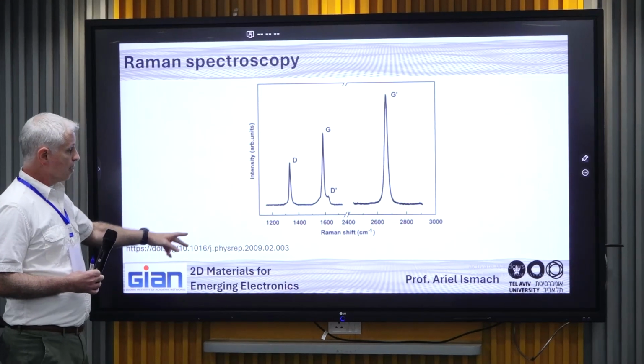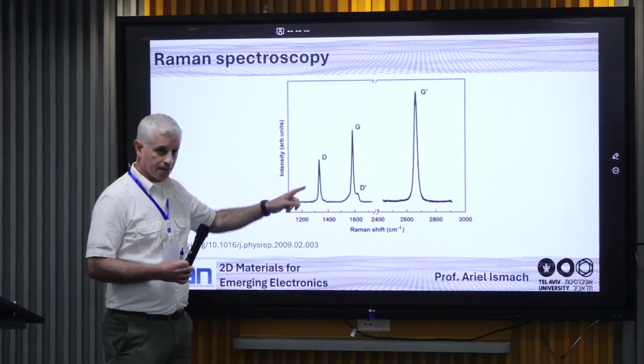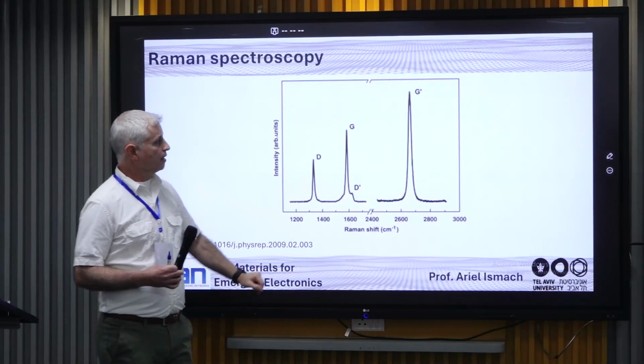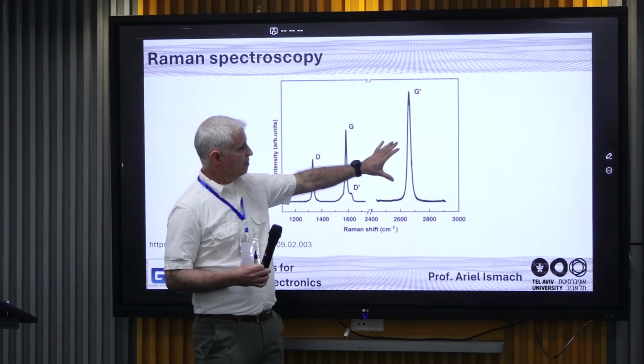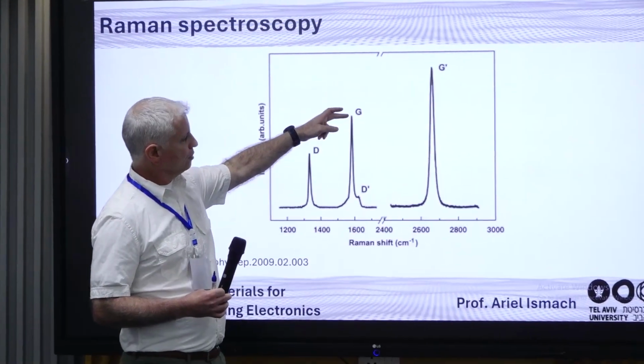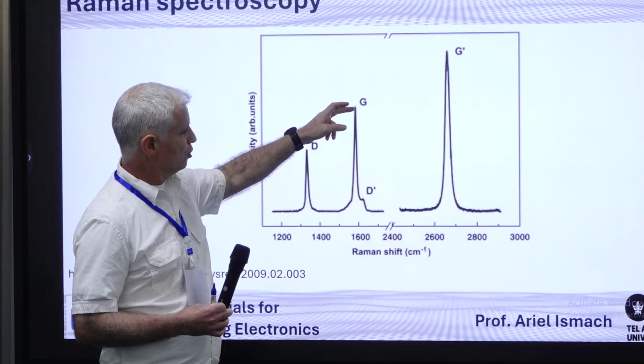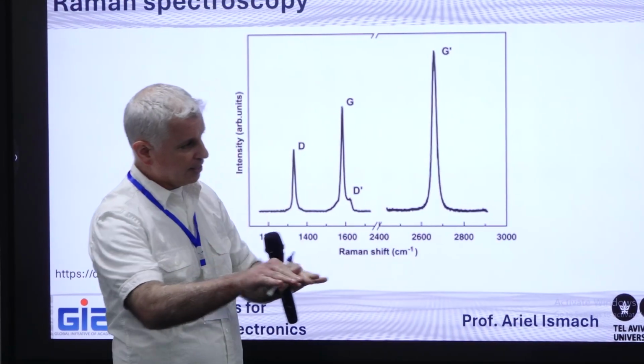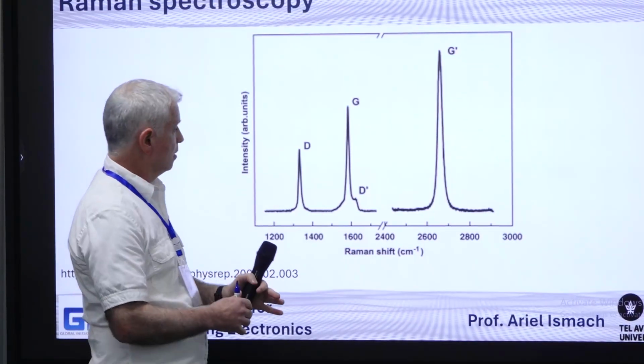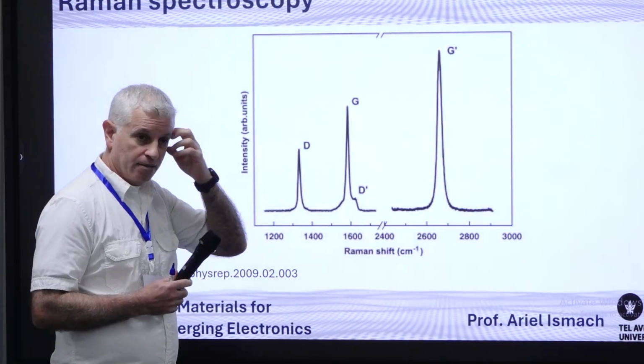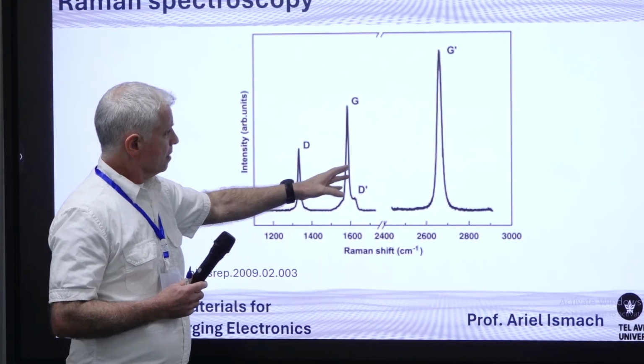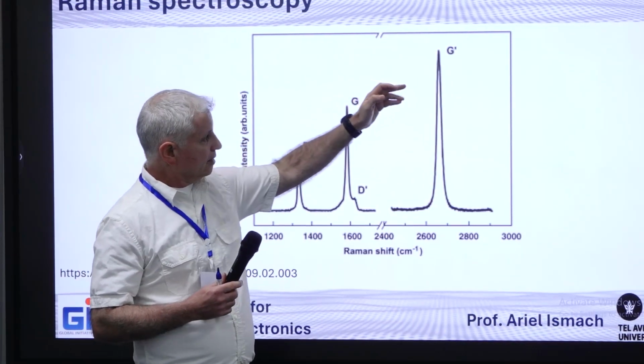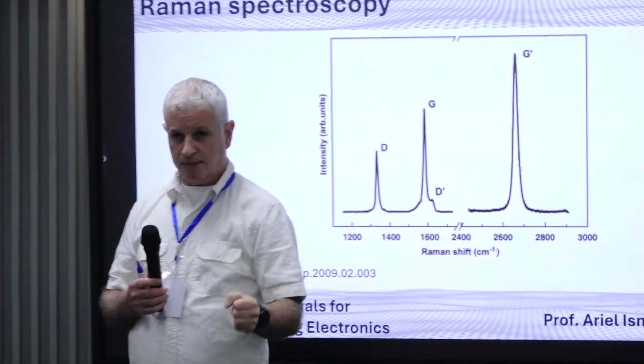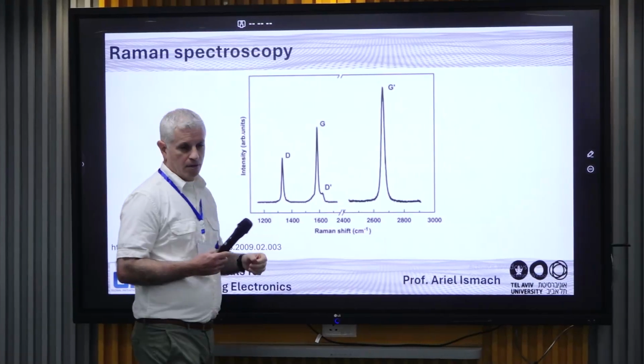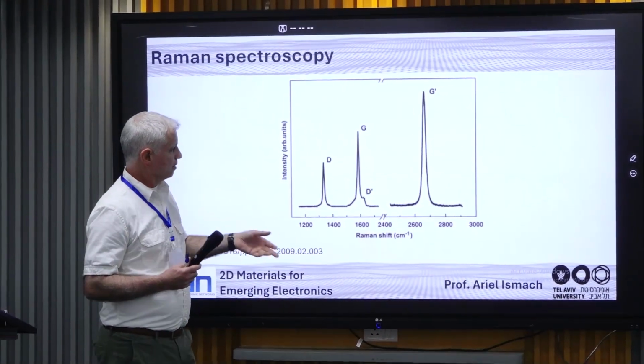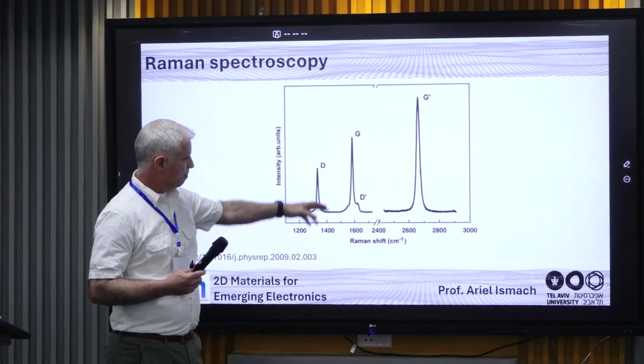And this spectrum is coming from a defective graphene. Look at the D peak. The D peak is huge. But a few things you can learn from this spectrum. First of all, that you have single layer. Why? Because of the ratio between the intensities: the intensity of the G mode, which is the in-plane stretching of the hexagon and is not sensitive to the number of layers, it's sensitive to many other things that we'll see in a second. So the ratio between this intensity and the G prime intensity, which is very sensitive to the number of layers, should be very small. G prime should be usually twice or more bigger than the G.